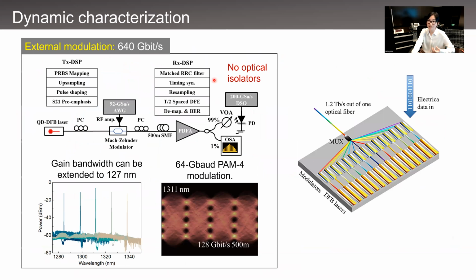So by virtue of the small linewidth enhancement factor of quantum dots, we are able to perform a system demonstration without optical isolators, and we got an aggregate transmission capacity of 640 gigabit per second, which is achieved by using 5 channels of the laser array with 64 gigabaud PAM4 modulation. So the current wavelength range was limited not by the quantum dots, but rather by the range of grating periods we currently use. So using a chirped design in the quantum dot region, the gain bandwidth can actually be experimentally broadened to 127 nanometers. So the laser wavelength can also be extended well beyond the current test range, and 1 terabit per second data transmission is achievable without an isolator.